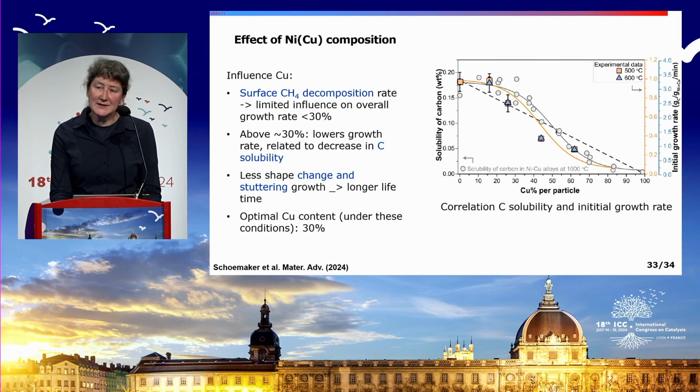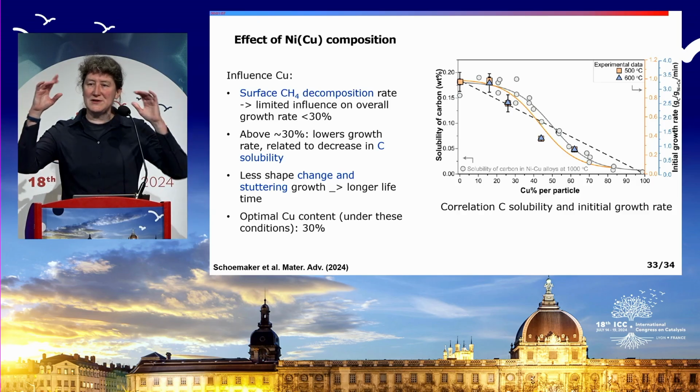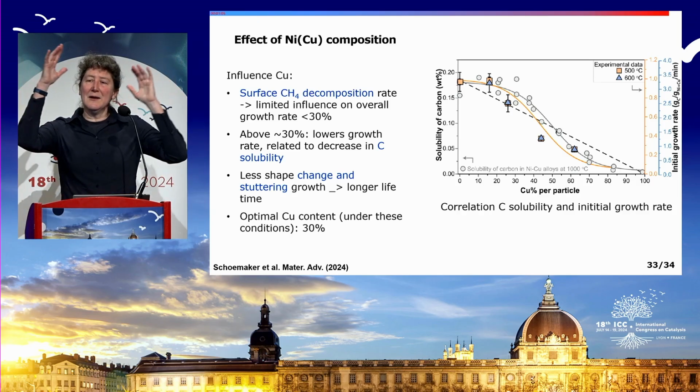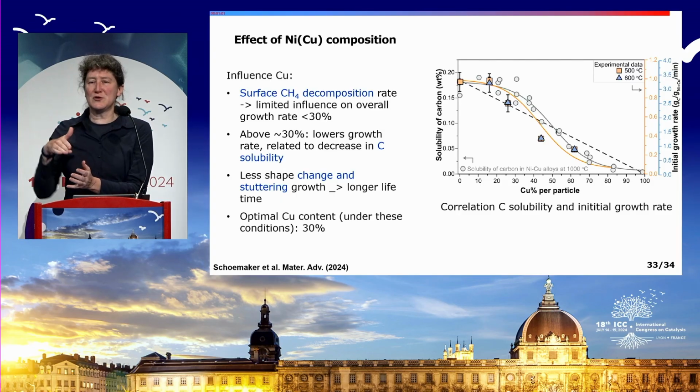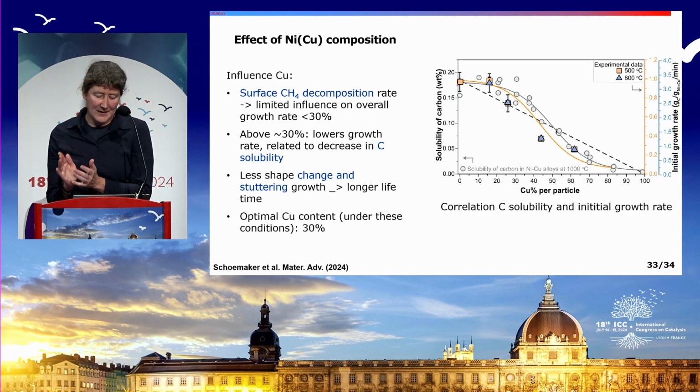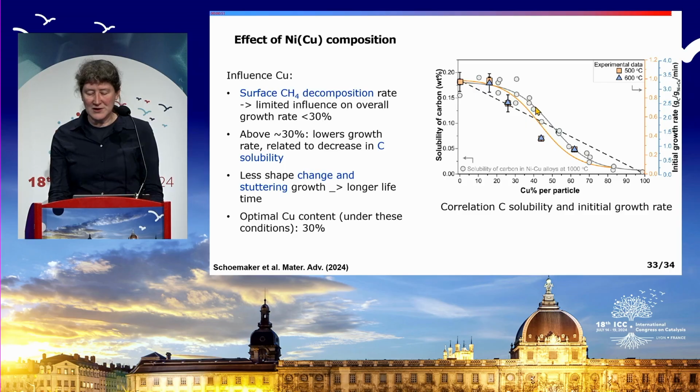And we correlated this to the solubility of the carbon. So actually the problem is that you decompose methane, but only on one side you're growing a nice carbon nanofiber. And you need to transport your carbon through the metal nanoparticle to this site. And this depends on the solubility of the carbon. And the solubility of the carbon in nickel actually goes down when you add some copper, but for a long time it stays more or less at the same level. And then just above 30% it goes dramatically down.